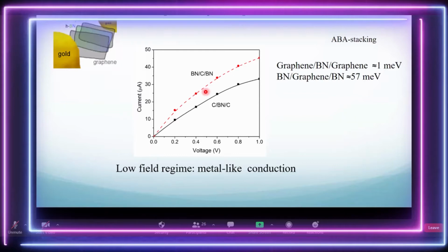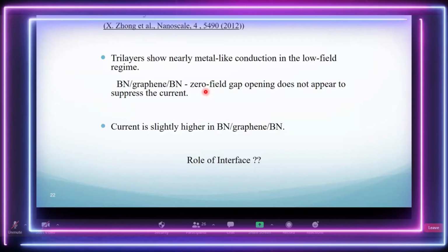So what it comes out is, the results are correct. Although the trilayers have a different energy gap, they show more or less the same metal-like conduction in the low field region. And even if you have a zero field gap or a finite gap, it does not suppress the current.